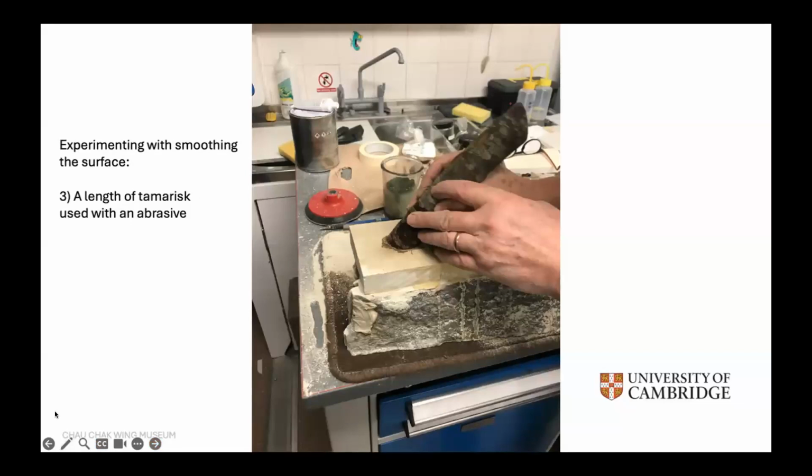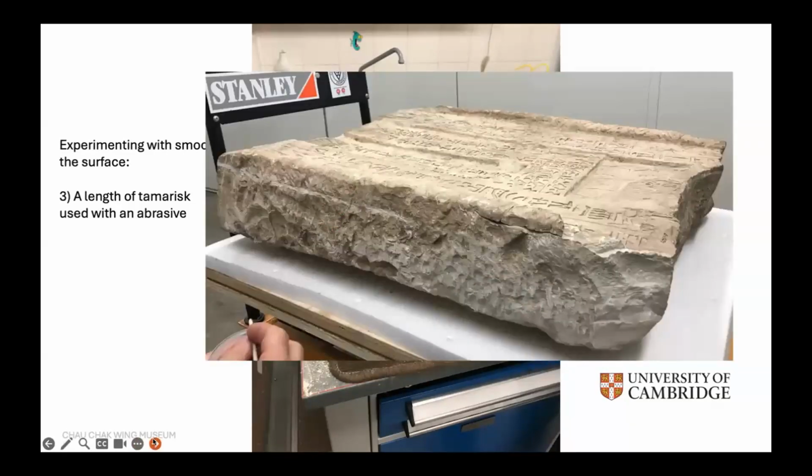Different abrasives were tried, including rutile, an oxide mineral composed of titanium dioxide, but this is too fine. Aluminium oxide, which smoothed the surface quite well, and ground emery, which also achieved a smoothed effect. However, none of these were as effective as the side of the chisel. This technique also caused a slightly undulating effect, which we can also see on Hemi-Ra's false door. But you don't get this effect from a rubbing abrasive block, which leaves the surface much flatter.